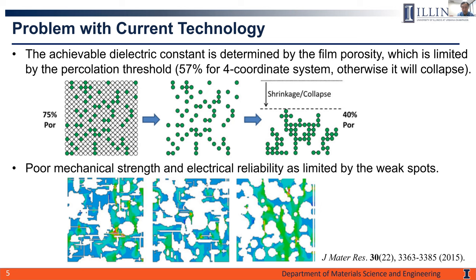However, it will be very difficult for such random pore structure as the porosity is theoretically limited by the percolation threshold. So mathematically, the percolation threshold for a four-coordinate system is only 57%, which means if the porosity actually goes above this threshold value, well, the original long-range connectivity of such random system cannot be maintained, and therefore the structure is going to collapse. So it will get the film porosity back below the percolation threshold.